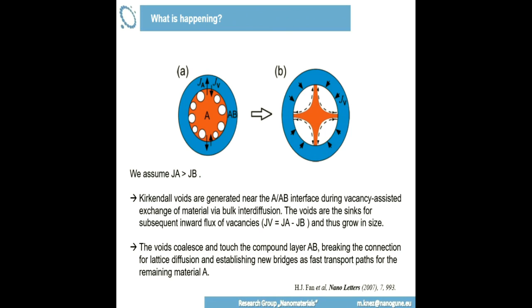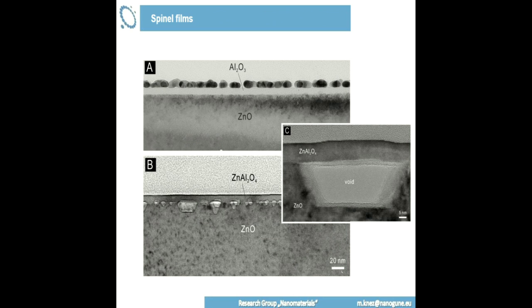And if you have this non-equilibrium, you can consider this being as movement of voids. So you are left behind with some voids. They are created because of this material diffusing quicker than this one. And those voids are going to merge at some point, and they will even enhance this effect then because they are going to act as sinks, energy sinks for the diffusion. Again, this is going much into diffusion physics. But the key point is, if you have such a material diffusion, ion diffusion, which is non-equilibrated, you will end up in having voids in the structure.